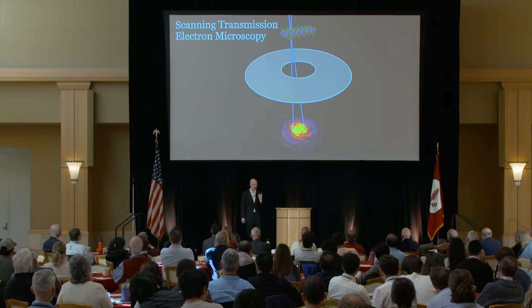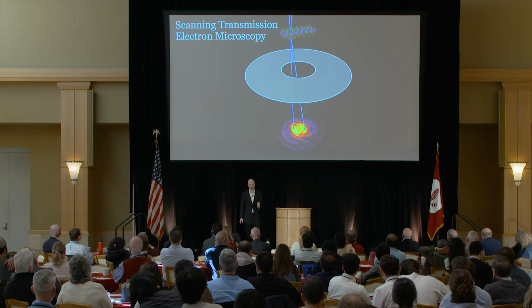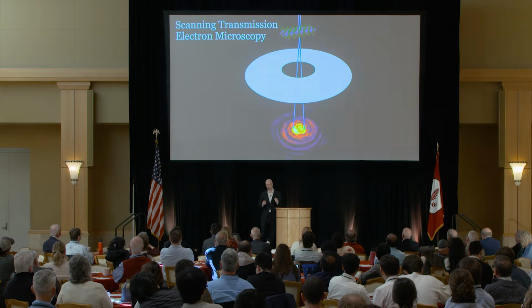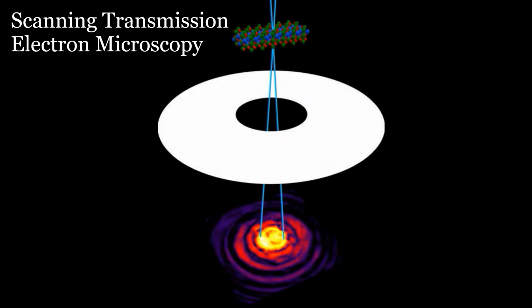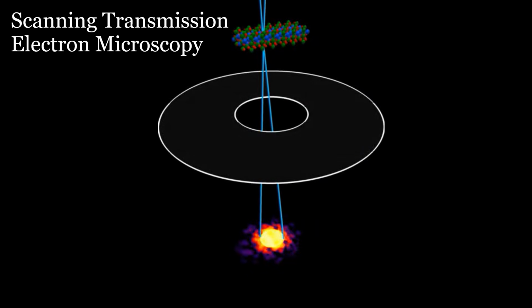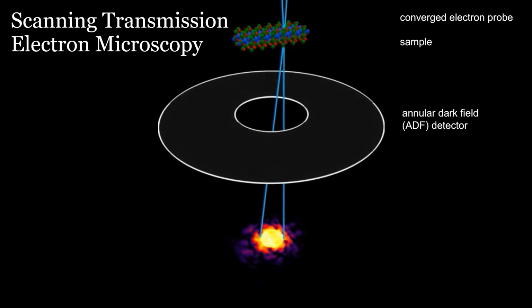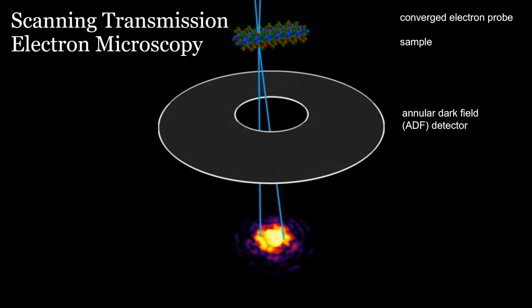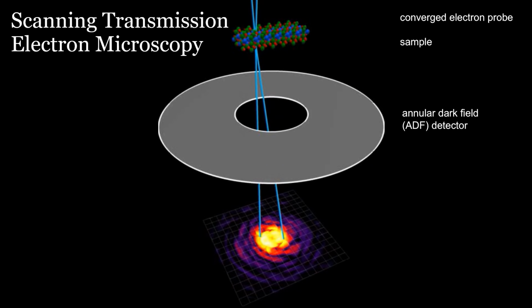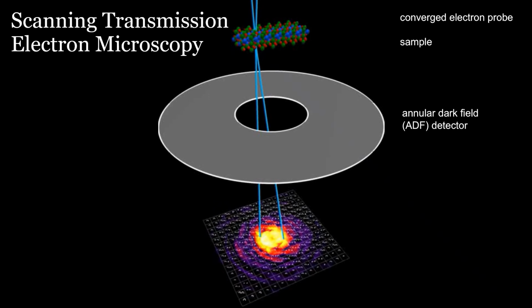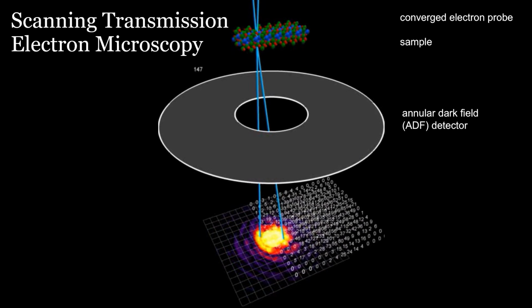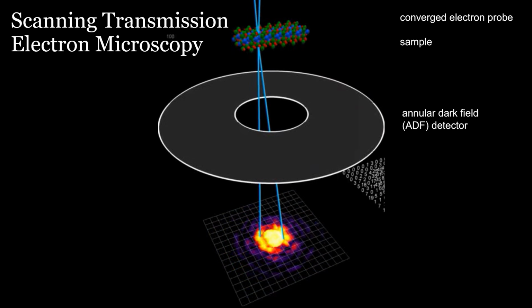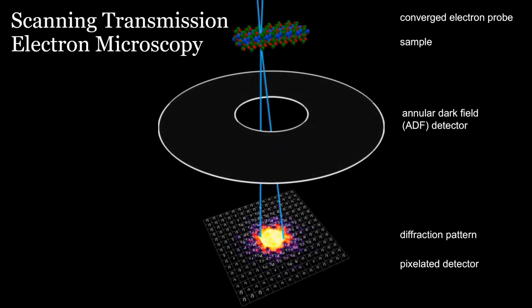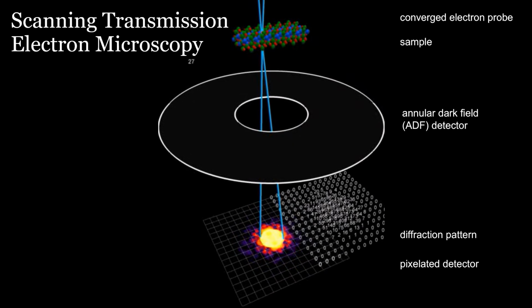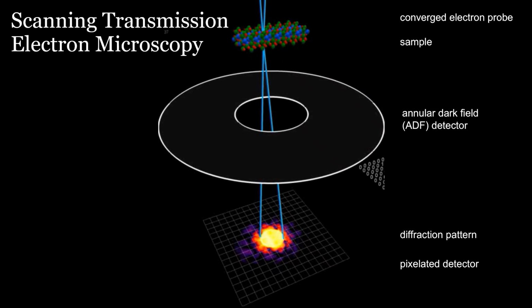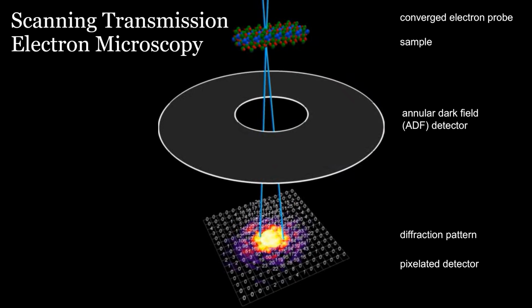Okay, so now I want to move to the main technique of my talk, scanning transmission electron microscopy. So conventional STEM, we would raster a probe across the surface, and you can see this big donut-shaped detector which would collect a single value at every probe position. We move the probe, record another image, move the probe, repeat. But if you look at the bottom, the diffraction pattern is much, much more complex. It has a huge amount of information. And now we can use those direct electron detectors to capture that full image of the diffracted probe, move on to the next probe position, repeat, repeat.